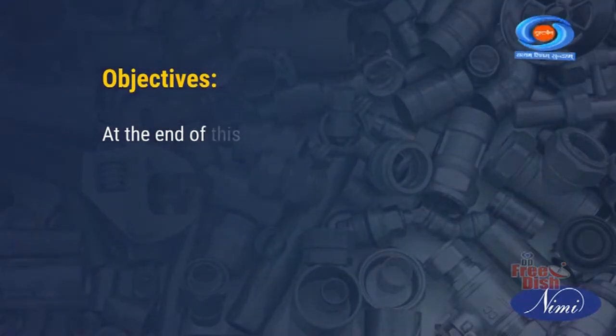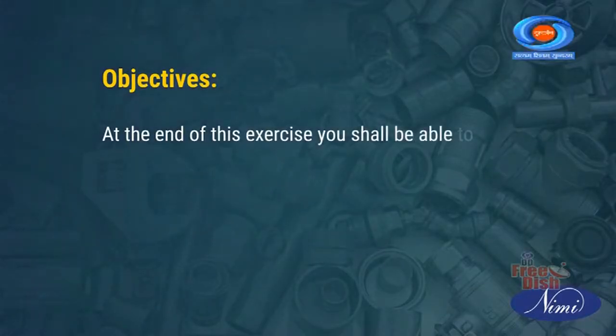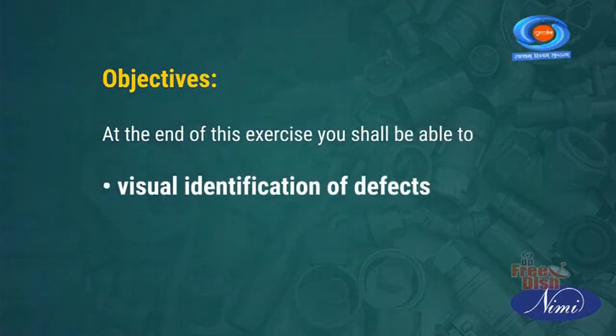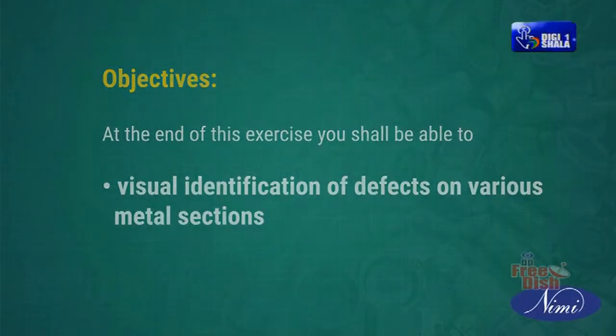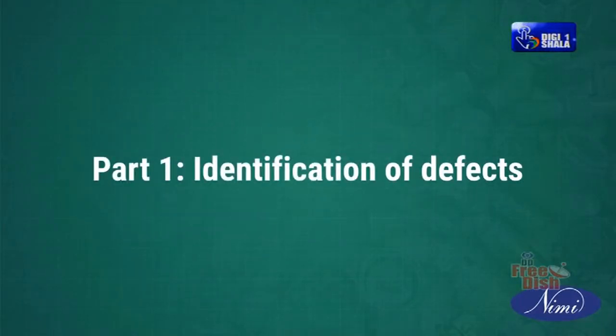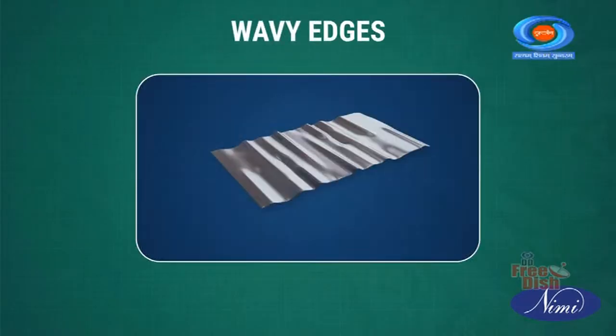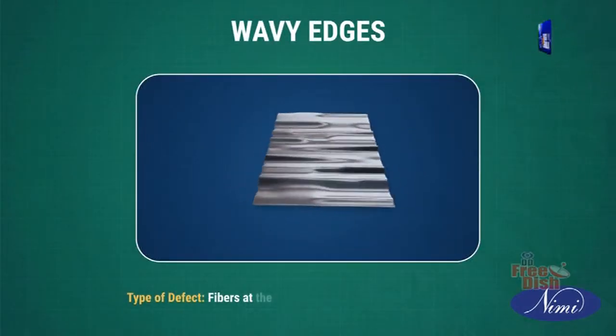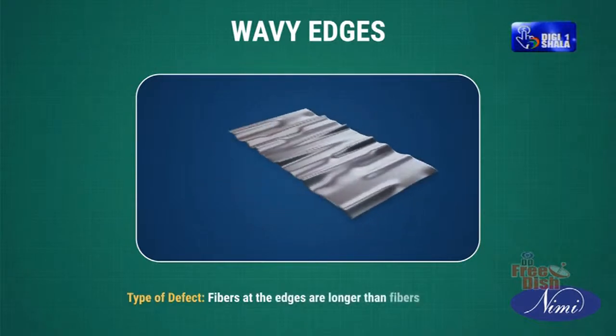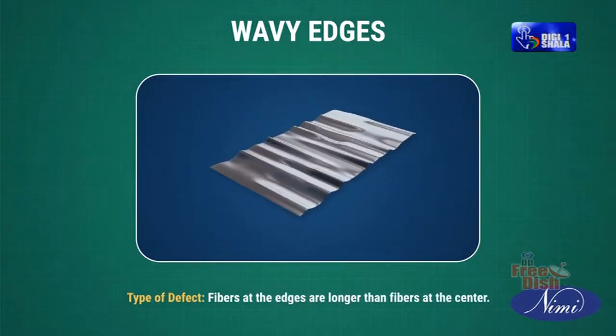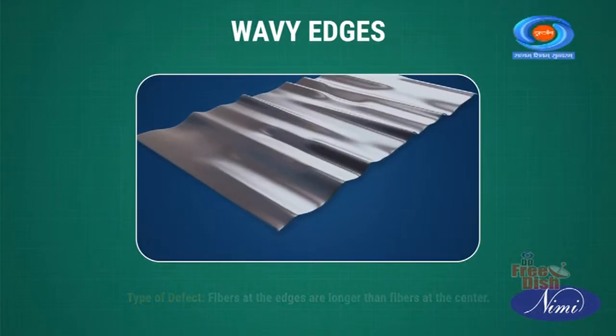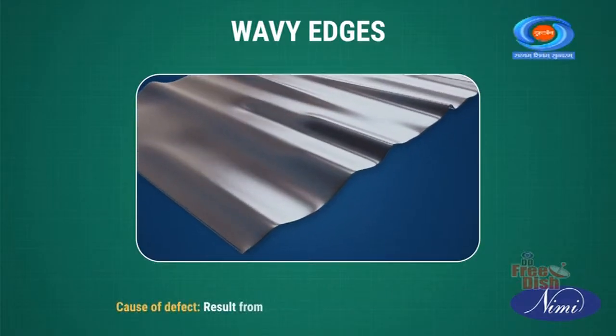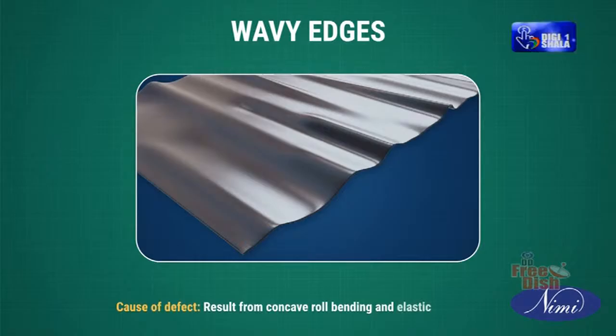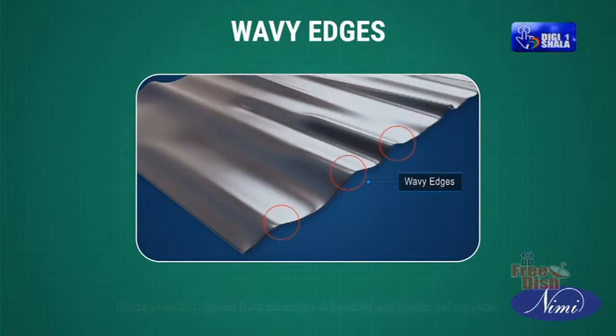Objectives: at the end of this exercise you shall be able to visually identify defects on various metal sections. Part 1: Identification of defects. Wavy edges. Type of defect: fibers at the edges are longer than fibers at the center. Cause of defect: result from concave roll bending and elastic deformation.